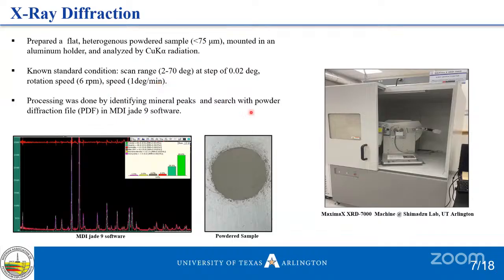What you have here, I don't want to go deep into this, but these are input parameters. For example, in the lab, I had to use input parameters like setting the voltage and current in a stepwise process to 40 kV and 30 mA respectively. And I also have to set the tubes, the tube and detector distance, and the two theta angles, which were set to continuous scan mode with a range of 2 to 70 degrees.